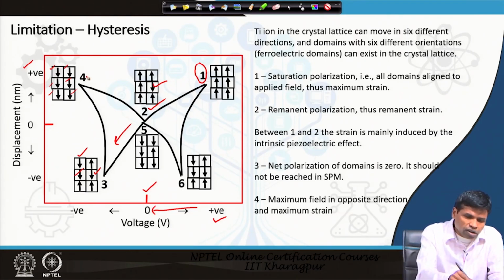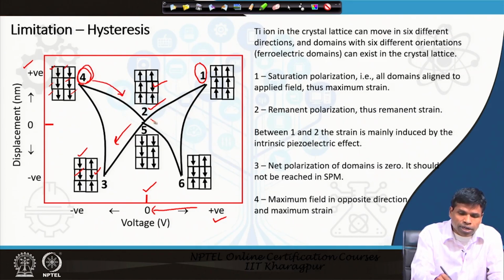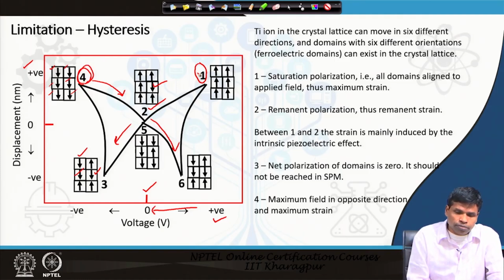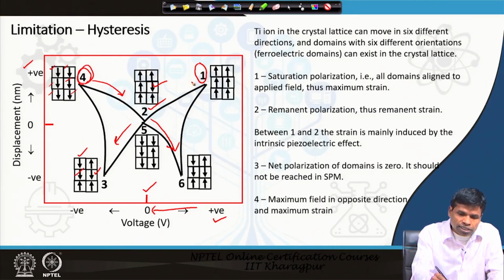And now, when we reverse the potential, when we increase the potential from negative to positive, those will not follow the same path they came. They are following an opposite, different path, 4 to 5, then 6, then 1. So, this is called the hysteresis behavior, and what it is showing is a butterfly type of curve. It is showing a butterfly type of curve, and between 1 to 2, when the orientation changes,